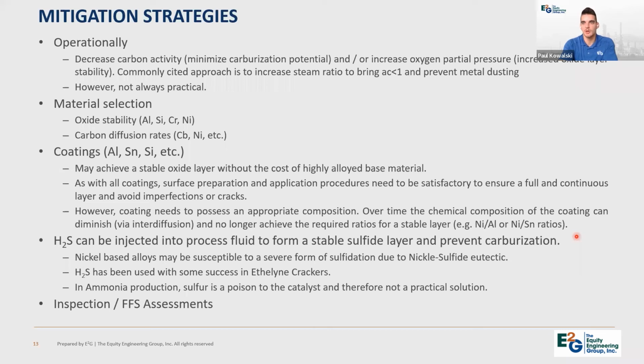Another commonly used approach is you can actually inject hydrogen sulfide into the process fluid, and this forms a stable sulfide layer on the surface of the material. If this sulfide layer is intact, then again, it's reducing the exposure of the base material to the metal dusting environment. And of course, metal dusting won't occur then.